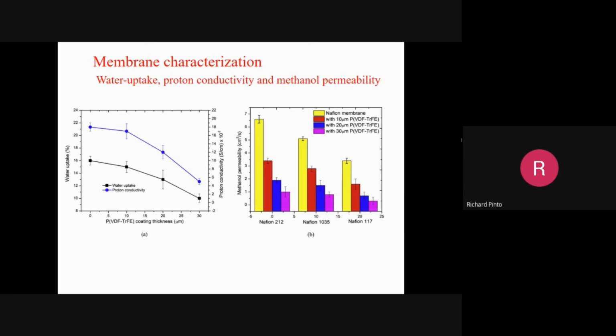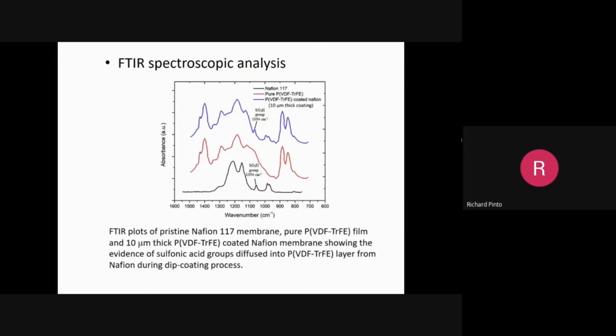So there's not much difference between uncoated and coated. At the same time, the methanol permeability comes down drastically. See here, both for this and this. It doesn't matter for this because this is already quite thick and you get very low power from the 180 micron one. So this is the key, and we have also applied for a patent on this, as I mentioned earlier. Now, what is the physics behind this?